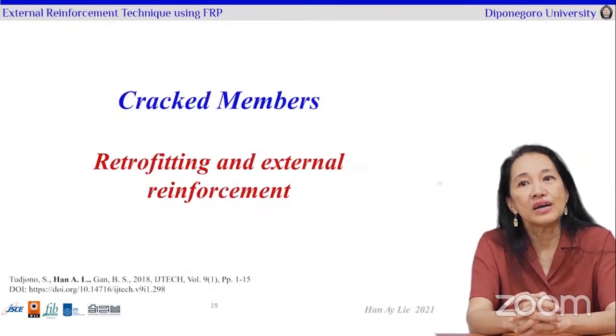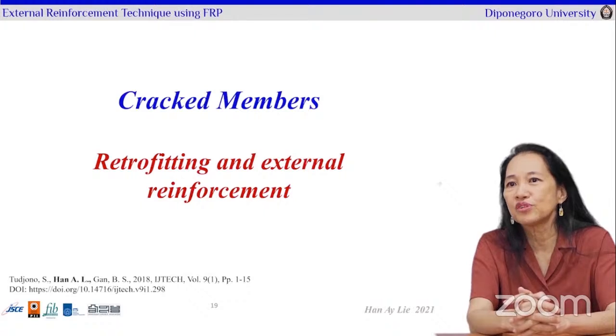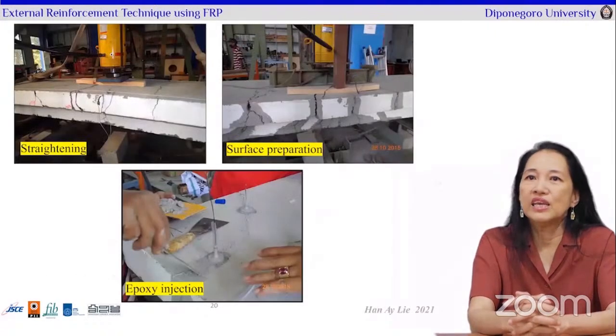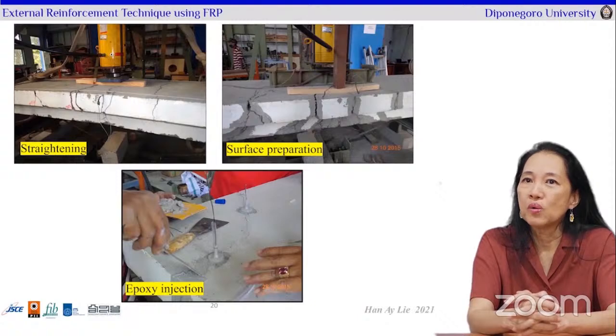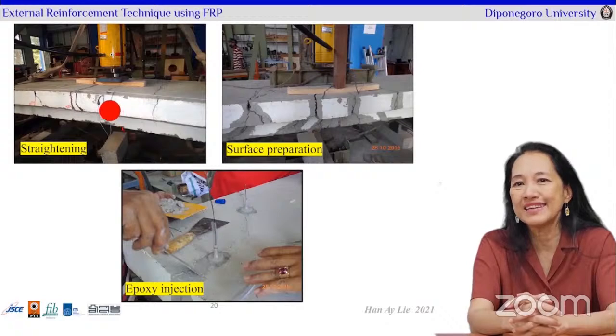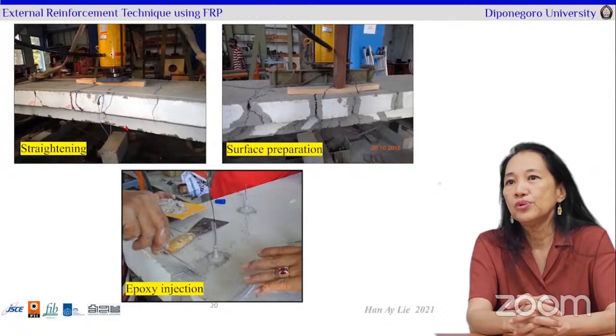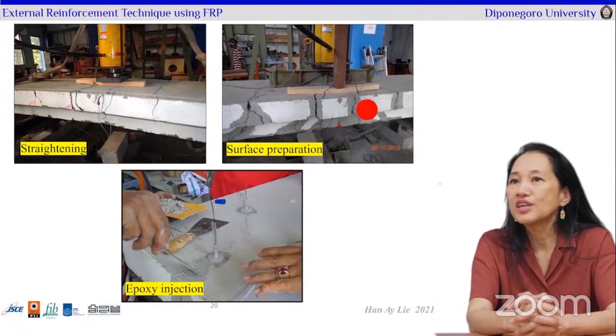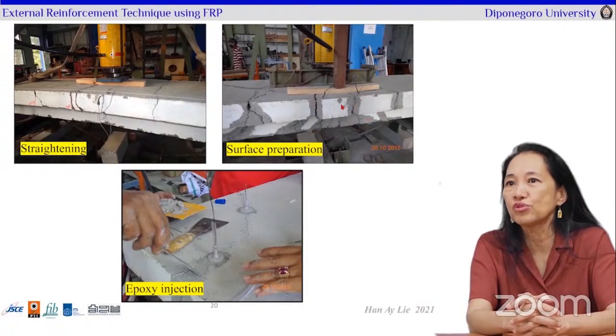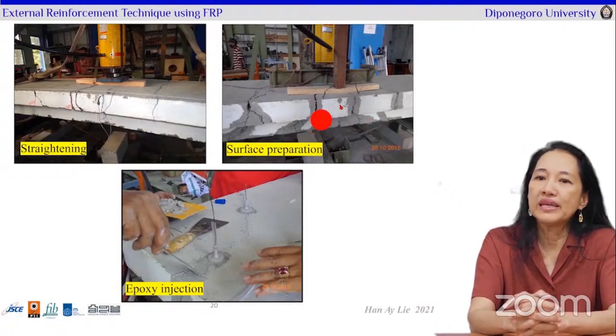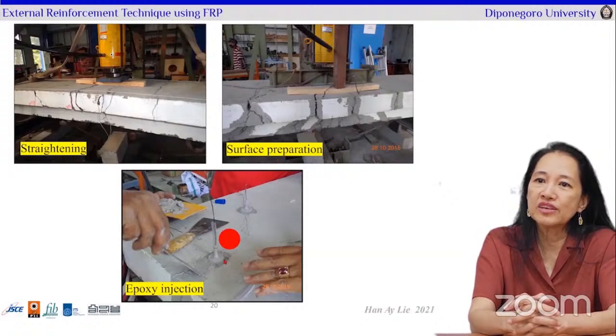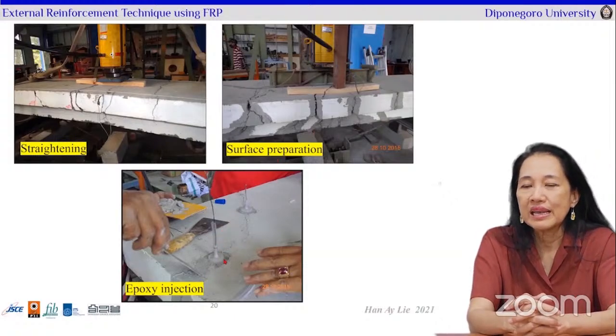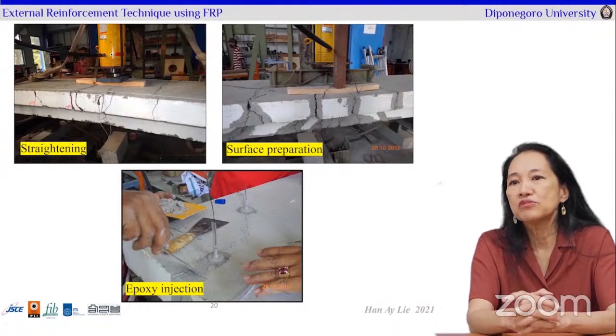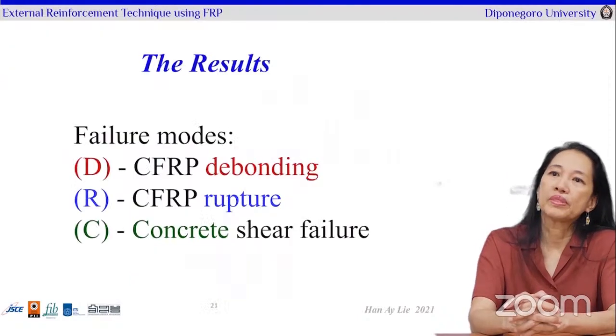We also have a retrofit and an externally reinforced member. Here we have the cracked beam, which did not collapse. First, you straighten the beam so that it's in the right position. You do a surface preparation by cleaning the cracks, cleaning the surface, and then we did an epoxy injection within the cracks. This is thanks to Sika, who has been supporting our research all year long.